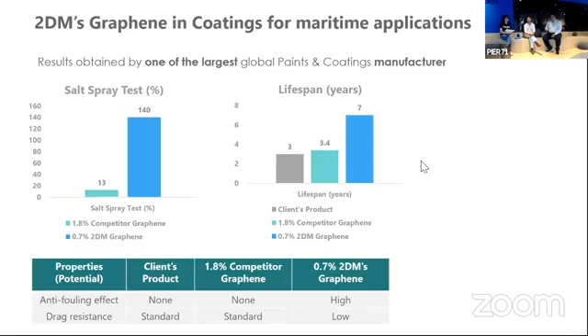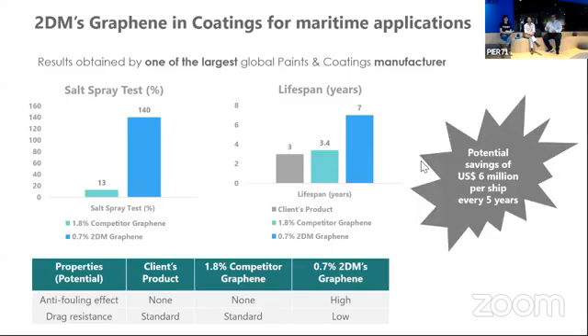And graphene brought some very interesting, we call it beneficial side effects. That is the anti-fouling effect. Fouling is very critical to the maritime industry because the barnacles attached to the hull can increase fuel consumption by up to 9-10% because they increase the drag resistance of the ship. And graphene plays a very important role in reducing the fouling and the consequent drag resistance.